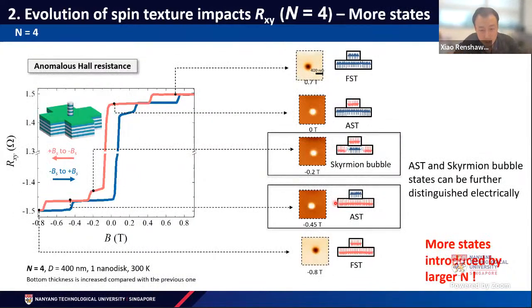We also studied n equals 4, meaning the bottom layer repetition is 4, as you can see from here. We can see this is more interesting because we have more transitions here, and of course we also identified the magnetic spin textures here on the right side. And we feel that n equals 4 would be the more interesting one because we can see a lot of features that we can potentially play with the magnetic states. So that's why we can potentially have more magnetic states.